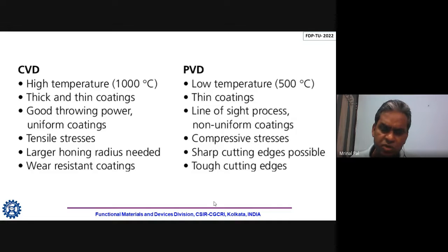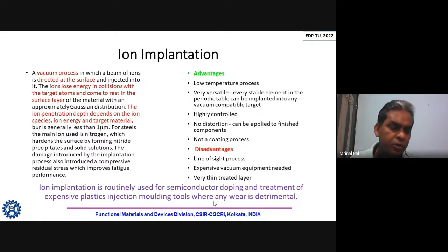So these are basically the differences between CVD and PVD, and depending upon your material and availability, you can use CVD or PVD. But let me tell you, almost every material can be prepared using PVD, but not every material can be prepared by CVD, because CVD is a high temperature process, and many materials actually evaporate before that. Because we generally use above 1800 degrees C, and as you know, a lot of materials will melt before that temperature. That's why CVD is restricted. It is only for hard coating and for materials which have a high melting point, like carbide, nitride kind of things. So I have grossly explained everything, and PVD and CVD I have also described schematically, so that you can understand all these processes under CVD and under PVD.